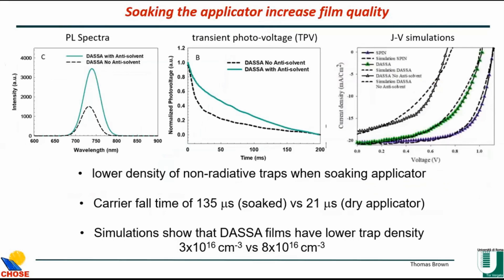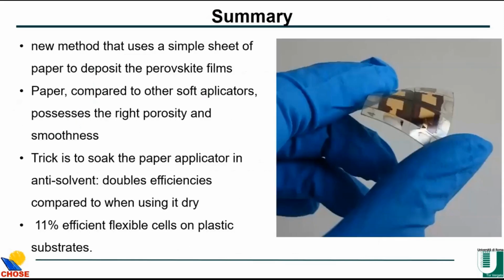And these are PL experiments which show that there's less defects when you use the anti-solvent soaked applicator. The fall time of the VOC is much longer. And we also carried out some simulations which show that the defect density is greatly improved when you soak the soft applicator in anti-solvent. It goes from 8 to 3 times 10 to the 16 centimeter to the minus 3.